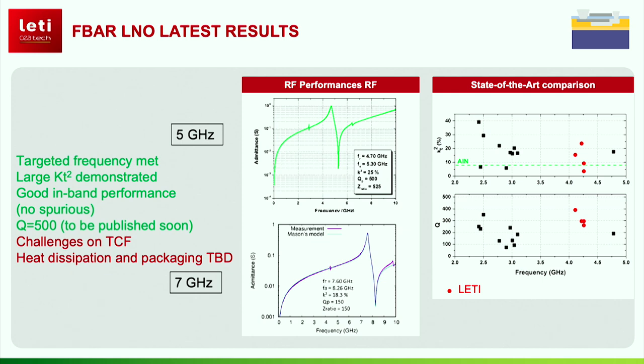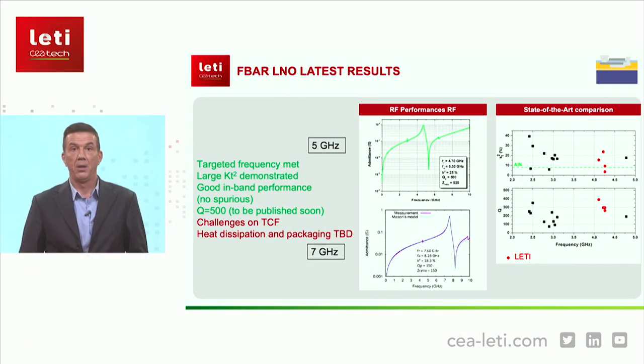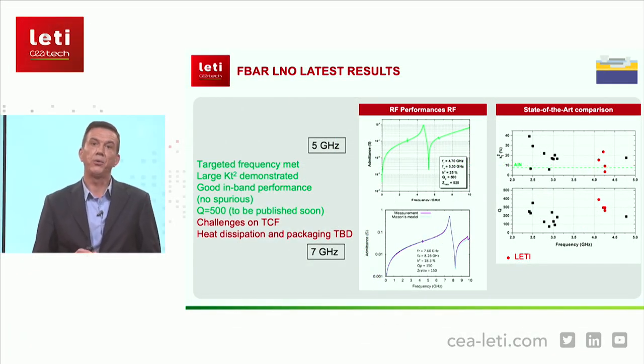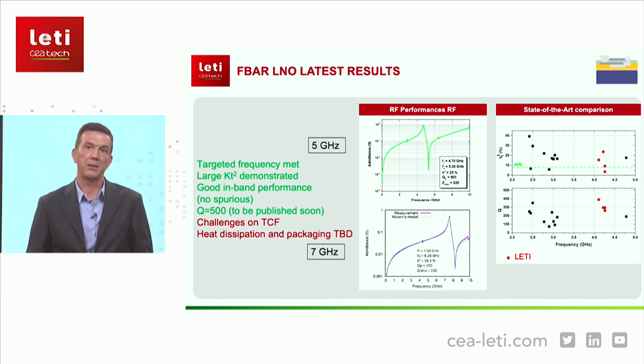Now let's also look at the results for the F-bar. Here we show three different resonators targeting respectively resonant frequency at 4.7 GHz in the green curve, 7.6 GHz in the purple curve, and 4.2 GHz on the right side of the slide with the red spot. The coupling coefficient at 4.2 and 4.7 are even higher than those achieved with SMR. It is a little lower when targeting 7.6 GHz, but that's expected.